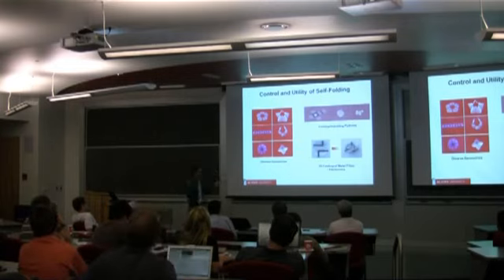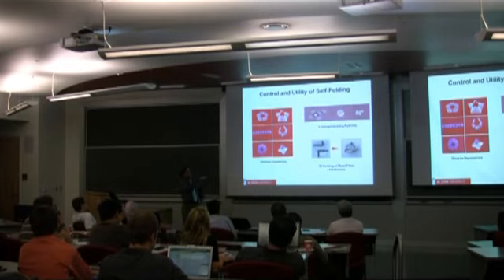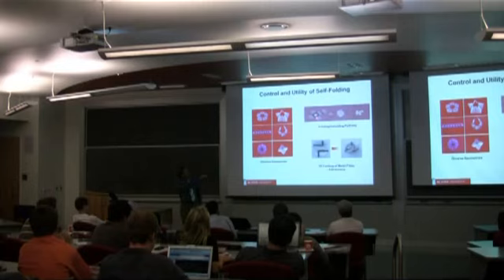So it's basically what you're doing is you're going from this state, which is very energetically unfavorable. You're folding it. By the way, this is a grain of rice, just to give you some size scale. So we put it in this little container, and then we put the whole thing in an oven, and everything shrinks. So it goes from this initial shape to something about 50% in size.